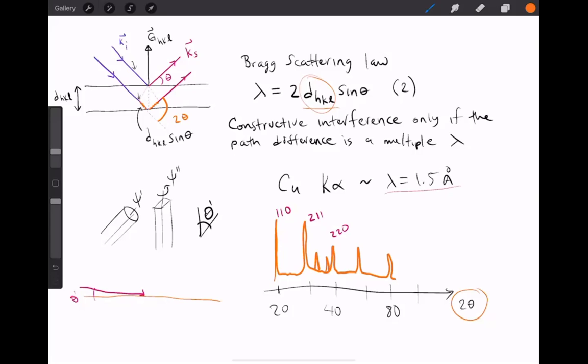All right, so there's two reasons for it. One is that the machine is not calibrated correctly. So that could be the reason for your shift. And then the other one is that you're making things. So the way that a lot of people do it is, let's say you come out with an XRD pattern, and then you compare it with a database. Yeah, it's shifted somewhere. Right, and then the shift could be because it's not calibrated correctly, or because the sample that you have is a tiny bit different from the one that is in the database.